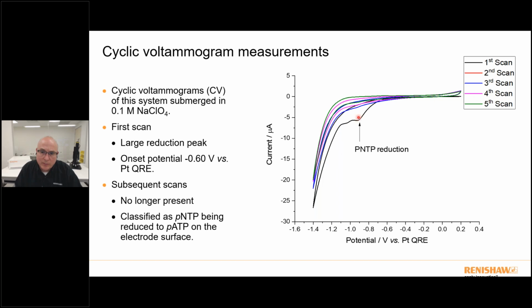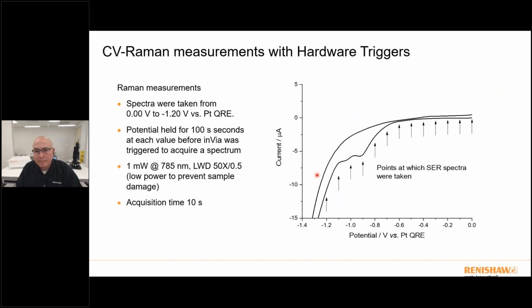So when we're doing these experiments, the first cycle that you go through, you see this very large reduction in the NTP, but the subsequent scans don't show that reduction anymore. So it's generally thought that you're changing from the nitrothiol to an aminothiophenol. And so we're starting to see those kind of applications there.